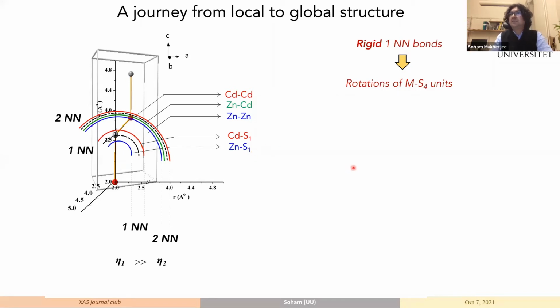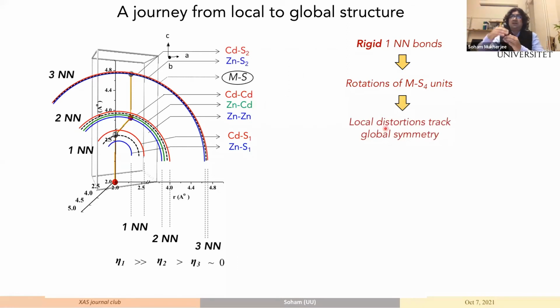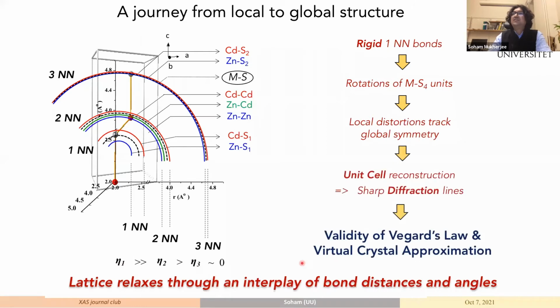the difference between these two distances gets reduced, as we have seen from the experiments. And then when you go farther down the crystal, so I'm approximating a lattice as spherical shells, you slowly progress and you see that from the percentage deviation, from the first to second to the third near neighbor, it gradually goes to zero. And that is why it validates the virtual crystal approximation and hence Vegard's law. So the lattice most definitely relaxes through an interplay of both bond distances and bond angles. And a simple approximation of lattice parameters to individual bond distances would be misleading.